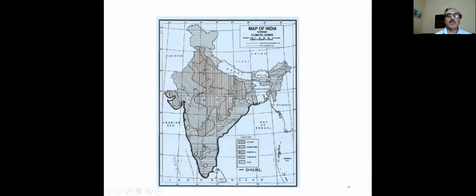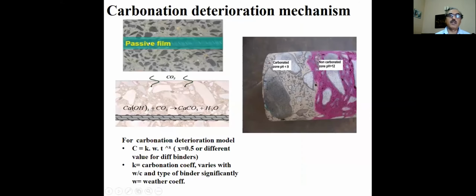Now, what happens in carbonation? When we do RCC work, the reinforcement has got a passive film. The calcium hydroxide present in the concrete, generated on hydration of the cement, provides a passive layer on the reinforcement. When carbon dioxide goes in, it reacts with the calcium hydroxide and disturbs the passive film, and corrosion starts. That is the main mechanism in most parts of the country.